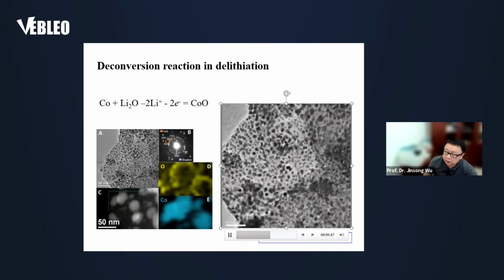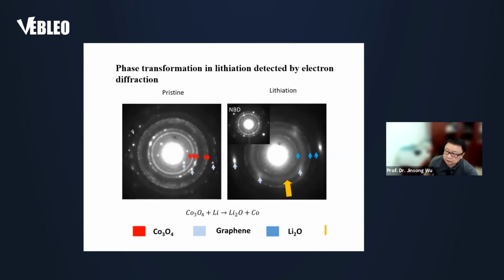And then we can also reverse the reaction, and reverse the bias. And then you see here, we can see clearly the formation of particles with very high contrast. By using both electron diffraction and the EDS mapping, it can be identified that those small particles are cobalt oxide. So this is a so-called deconversion reaction. And by using the diffractions, we can identify that the lithiation product is lithium oxide, and we have a highly diffuse scattering ring, which is due to the small metal cobalt nanoparticles.